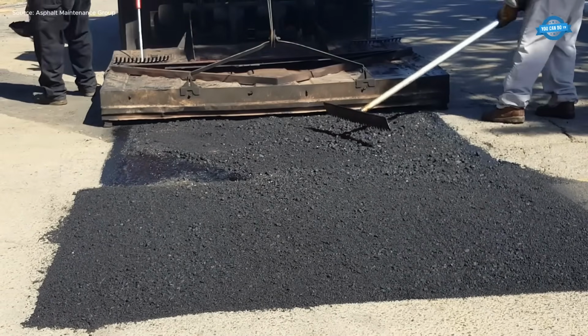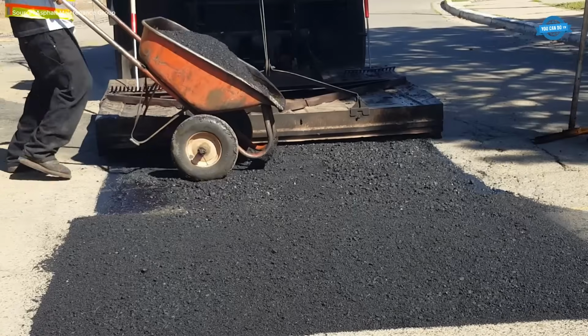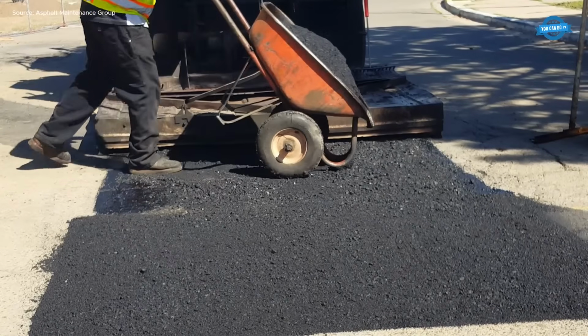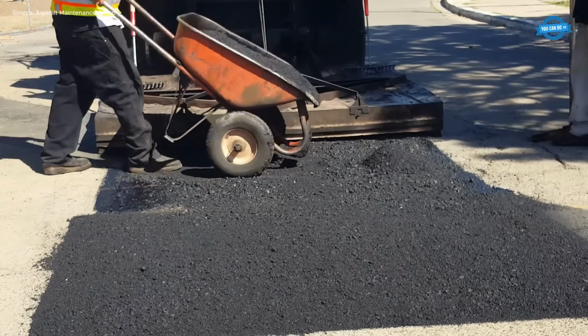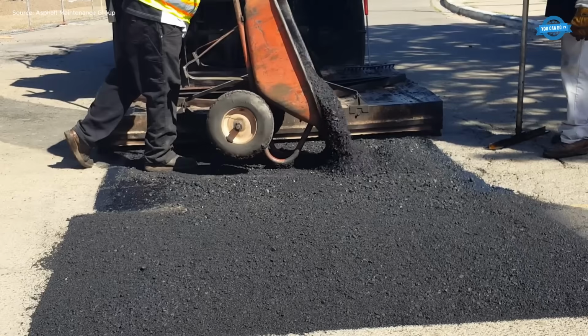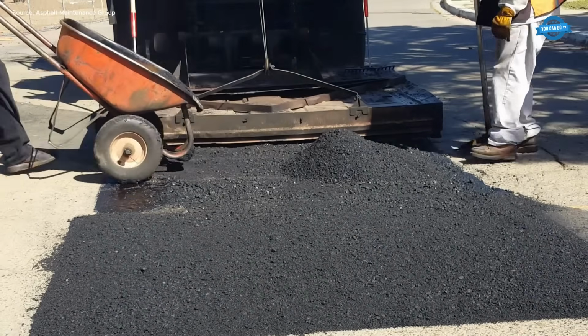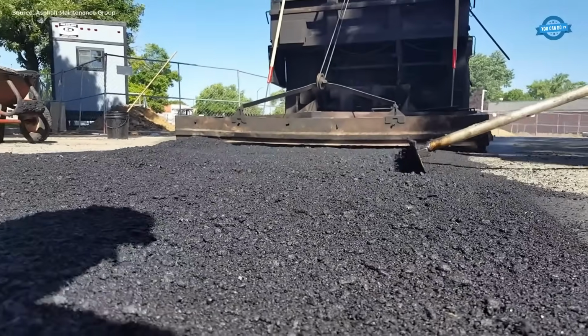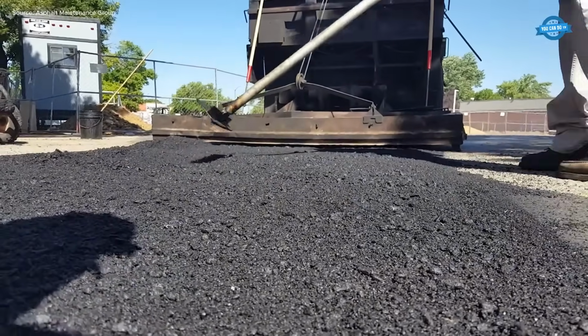Work from the edges inward to ensure even compaction, checking for a slight bump on the surface to promote runoff. Continue compacting until the patch is flush with the surrounding pavement, typically achieving 95% of the maximum theoretical density.